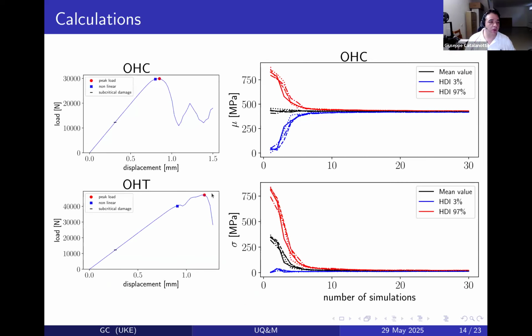So what do we do? We run a simulation, for example, open hole tension or open hole compression, as you have here on the left. And you can have the quantity of interest that you want. There I selected the subcritical damage. So it's when you have damage in the matrix or the delamination. And also there is the first nonlinearity, and there is also the peak load. So these are some curves that are representative of some analysis. And what I do is I perform Bayesian analysis.